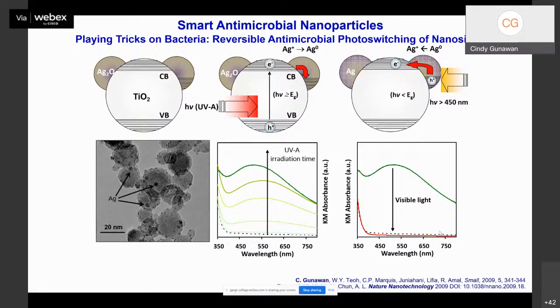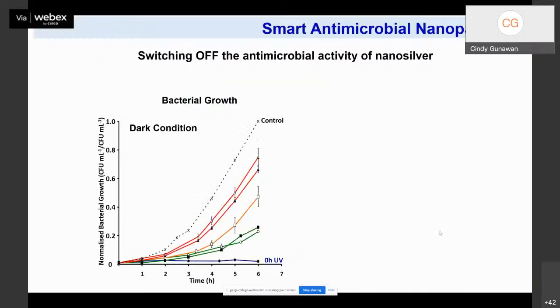So you might be asking questions now. Okay, so we have used this photo switching technique to manipulate the oxidation state of silver. But how can this actually translate to the manipulation of the antimicrobial activity? So we use a model bacteria to test this. We use E. coli as our model bacteria, and we expose the E. coli to these particles. So first, let me show you the switching off of the antimicrobial activity of nanosilver.